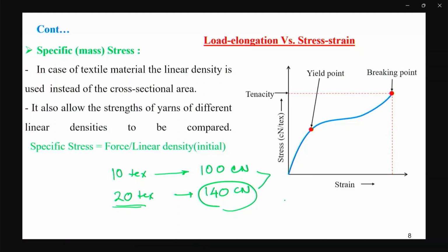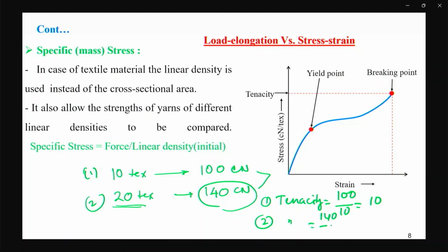If we want to compare, in that case we have to get the tenacity value. So, let yarn 1 be 10 tex, yarn 2 be 20 tex. For yarn 1, the tenacity we will get is 100 centinewton by 10 tex, so 10 centinewton per tex. For yarn 2, the tenacity will be 140 centinewton by 20 tex, so 7 centinewton per tex. Although yarn 2 with 20 tex has got higher breaking load, if we compare the tenacity, it is lower than yarn 1, which is 7 centinewton per tex.